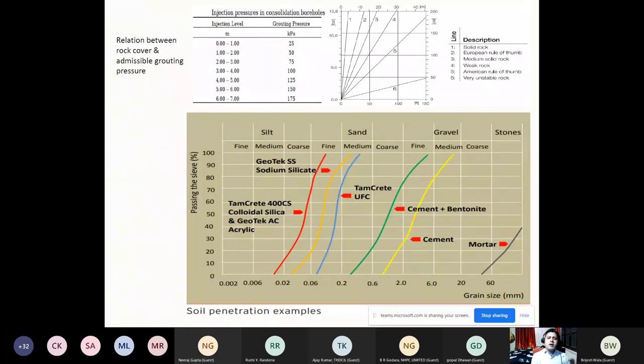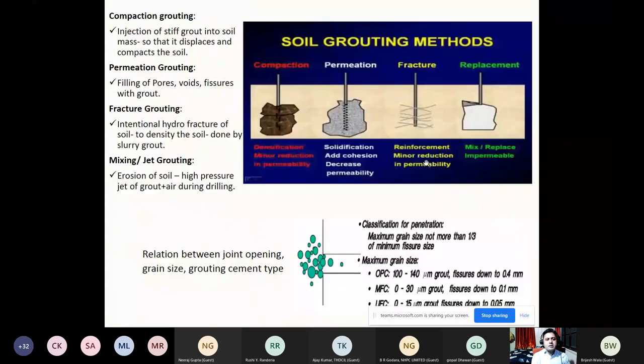There are some soil grouting methods: compaction grouting, permeation grouting, fracture grouting, and mixing jet grouting. I will not go into detail. I will be a little faster, because this is just the type of grouting in soil which we are treating and permeating, and which type of material you are pouring. Like OPC, you can use for 0.4 mm size of fissures. Like 0.1 mm fissures, you can go with the MFC. Like 0.05, a 50 micron size of fissures, you can go with ultrafine.